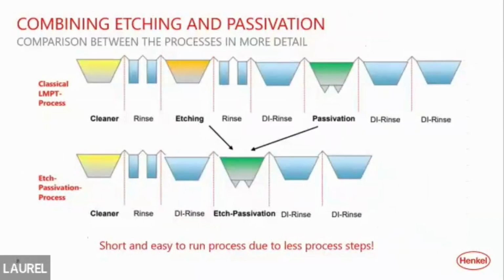On the top here is a classic light metal pretreatment process. And this is what I've been working on for the last couple of years. Light metal pretreatment process, classic cleaner, and depending on your water, you can use city water. Then we would use an etching or a deox stage. The terms are used kind of interchangeably there. Rinse, then a DI rinse before your passivation stage, also known as conversion coating stage.